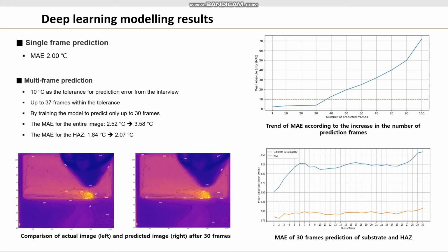So we set 10 Celsius degrees as the tolerance for prediction error, from interviews with experts operating laser cladding machines. As you can see in this figure, the SimVP laser cladding model can predict up to 37 frames within the tolerance. However, the mean absolute error increased rapidly after the 30th frame. So the experiment was conducted by training the proposed model to predict only up to 30 frames for stable prediction accuracy of the model.